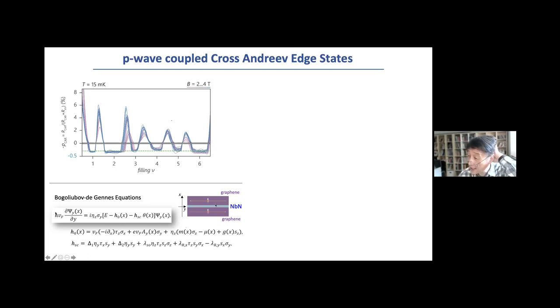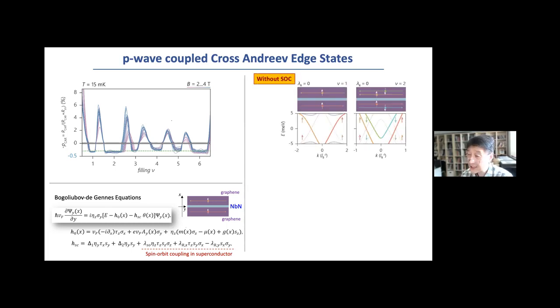It turns out it is very important that we include, especially for nu equal 1 type of things, quantum edge state where spin is polarized, including the spin-orbit coupling inside of the superconductor, because niobium is a heavy metal, and we expect there's a reasonably strong spin-orbit coupling. That is very important because without that, there is no way I can make the decoupling between the 2 spin polarized edge states in the nu equal 1, right? Basically, I need to form the singlet, the pairing. Therefore, I have to really remove the spin indices, or make spin not a good quantum number anymore, by including this spin-orbit coupling.